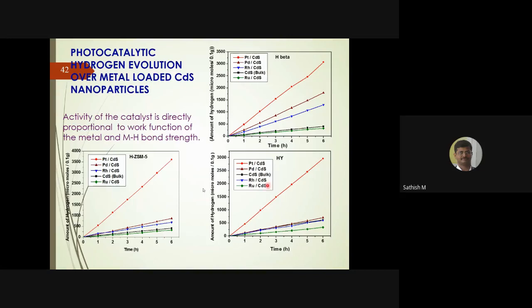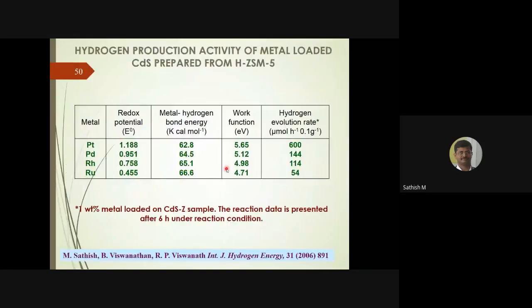We have also measured with different catalysts prepared from different materials. More importantly, we put different co-catalysts. As I told you, we put platinum, palladium, ruthenium, rhodium. We have correlated how this activity varies with respect to the redox potential and also the metal hydrogen bond. The metal hydrogen bond should not be so strong. For example, if the platinum hydrogen bond is so strong, then the hydrogen liberation will be reduced. Also the work function of the metal: we have correlated all three parameters with the hydrogen evolution. But this is more on fundamentals. If some of you are interested, maybe you can go and read this paper.